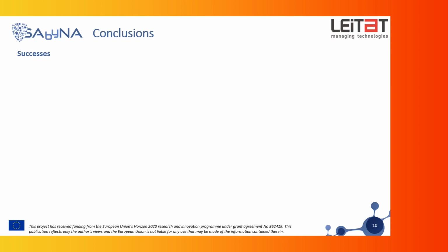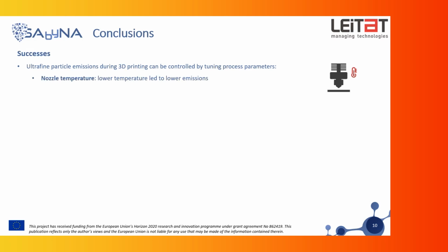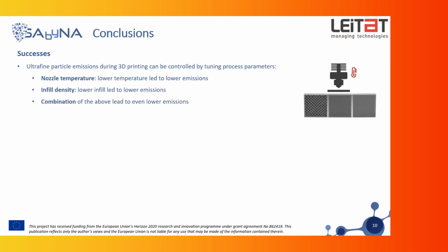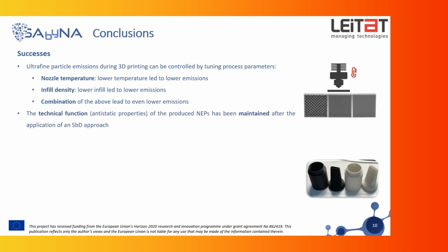Right, and to conclude, some successes: the ultrafine particle emissions during 3D printing can be controlled by tuning the process parameters like the nozzle temperature, where lower temperatures lead to lower emissions, and lower infill density leads to lower emissions. Their combination leads to even lower emissions. And the technical function of the antistatic properties in the specific case of the produced nano-enabled product has been maintained after the application of the safe-by-design approach.